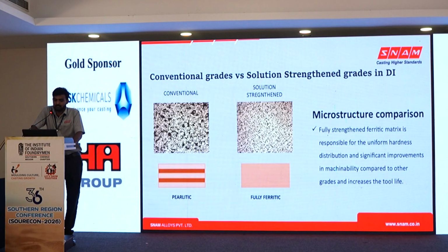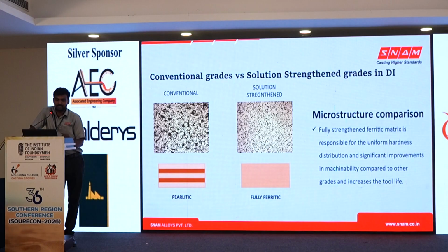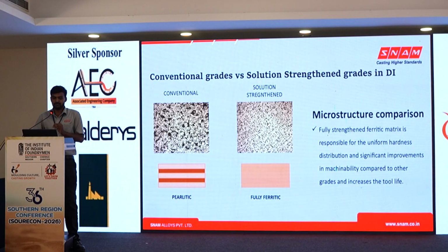So when we see the microstructure of conventional grade ductile iron and SSFDI, in SSFDI we can see fully ferritic matrix which helps us to achieve homogeneous mechanical properties throughout the casting section, and it also helps in easy machinability, which will finally help in improving the tool life. But in case of conventional ductile iron, we have pearlitic and ferritic matrix, so it makes the material somewhat brittle, and when compared to SSFDI, the machinability will be difficult in conventional ductile iron.